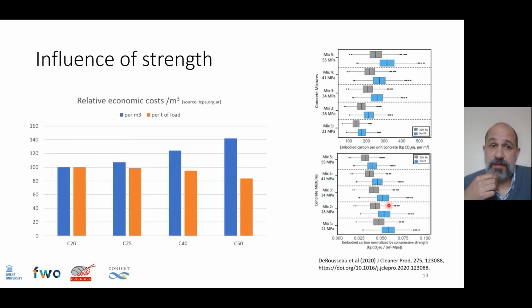Here we can also see the effect of strength on relative economic costs. This is an estimation for Argentina, where we see that as we increase the compressive strength from 20 megapascals to 50 megapascals, of course the cost per cubic meter increases, but when we consider it per ton of load that this concrete will be resisting, we can notice a reduction in the costs. So increasing the strength level of concrete in structures is not only beneficial for sustainability, but also for economy of the construction.